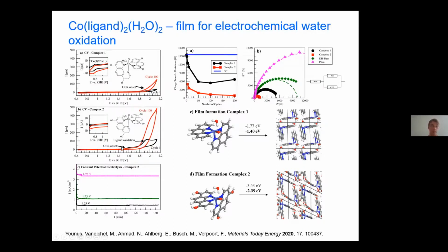Complex 2 had a quite low OER onset potential. Both after one cycle and also after 100 cycles, the current starts flowing at a low potential versus the reversible hydrogen electrode. What we also saw in electrochemical impedance studies is that the charge transfer resistance of complex 2 is much lower than for complex 1.